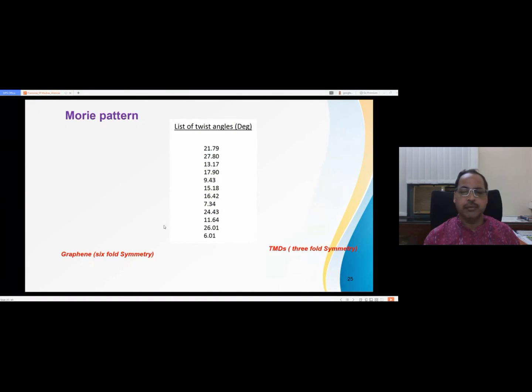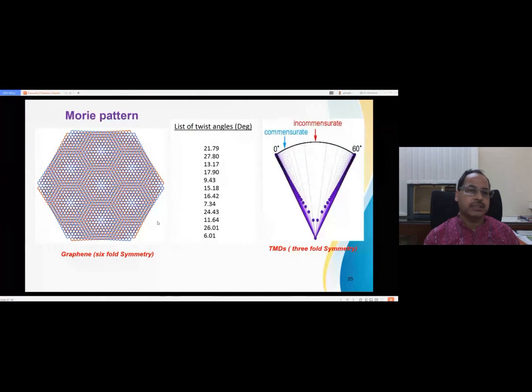Now you see what is really happening. With the help of our theoretical colleague, we do the band structure calculation. You can see a famous Moire pattern. What is this? This is your hexagonal graphene. If you put another graphene layer, you can rotate it up to a maximum of 30 degree because it is 6-fold symmetric. At some commensurate angle, you can get the Moire pattern, a very beautiful butterfly pattern you can see here. This is called the Moire pattern. At that angle, you can create your superlattice, and then you can do the band structure calculation to find all the electronic bands, how they vary.